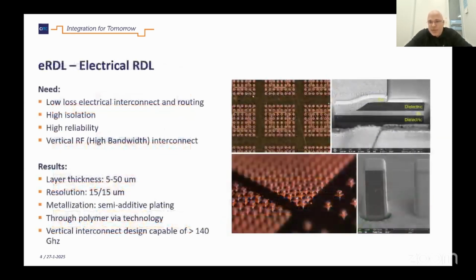This shows our first results of the electrical interconnect. Just some highlights: by this additive manufacturing process, we achieve a resolution of 15 micron line width with 15 micron spacing. Bear in mind that this is a pure additive process. We do not do any etching, we do not wash any material away, we only print what we need, so it's a much more sustainable technology. With this technology, we are capable of making high aspect ratio vertical interconnects, and with certain designs we can go beyond 140 gigahertz, so we can really boost the data rate from such packages.